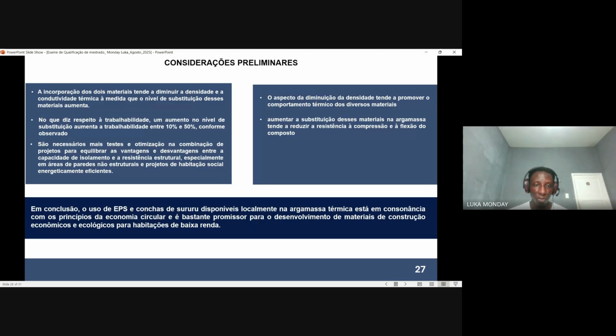Also, it is necessary to optimize the combination of these materials so as to balance the individual property with respect to the thermal insulation aspect and the structural aspect of this material, so as to minimize the level of cracks when used, and also to better the energy situation of this building. As the density of this material decreases, the thermal conductivity also decreases in the same way, making them better thermal insulation materials.